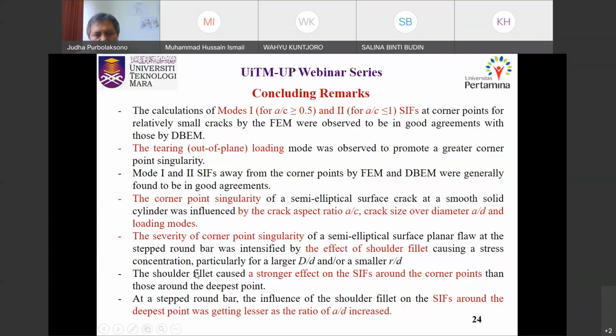As for the shoulder fillet, we can see from the graph that it had a stronger effect on the corner point rather than on the SIF around the deepest point. And the last one, we can also notice previously that the influence of the shoulder fillet on the stress intensity factor around the deepest point is getting lesser when the ratio A over D, the ratio of the crack depth over the diameter of the cylinder, is increasing.